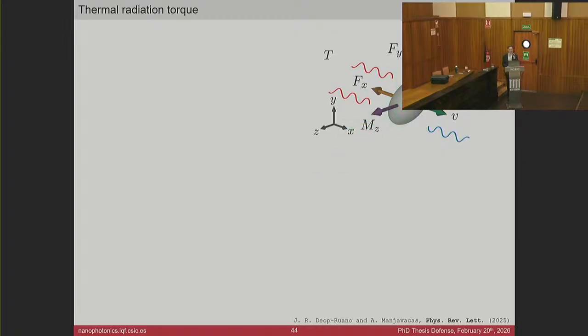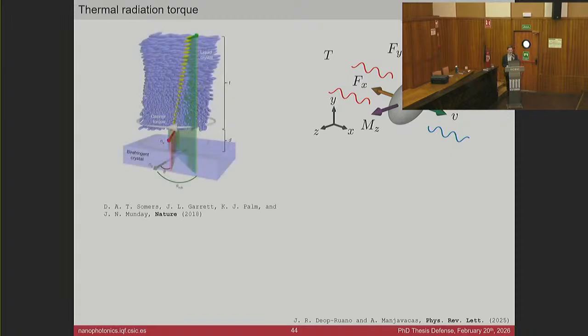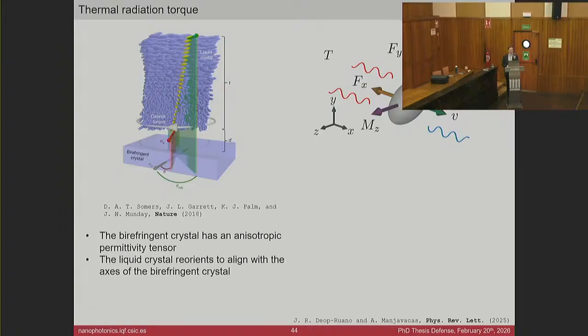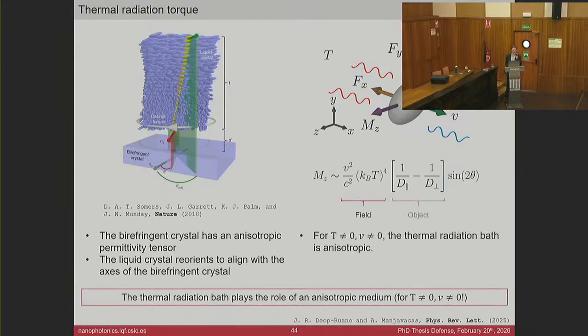There is a torque. So let's understand why this torque appears by means of a known example. This other paper that I showed to you before, in which we have a first anisotropic object, which is a birefringent crystal, and we have a second anisotropic medium, which is this liquid crystal that can reorient with respect to the birefringent crystal. And because of these two anisotropic media, a Casimir torque will arise. Now, in our case, we actually have two anisotropic media because we have an anisotropic field because of the Doppler shift, and of course the anisotropic character of our object because of its geometry.